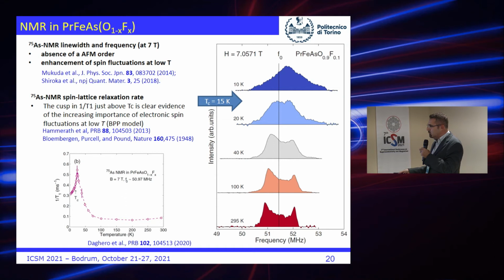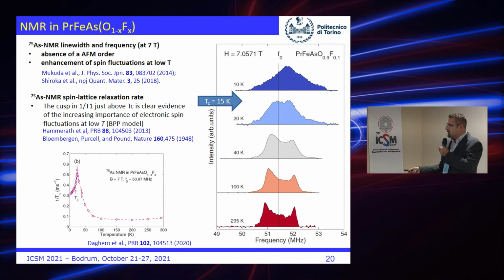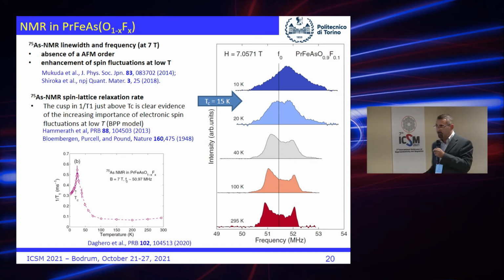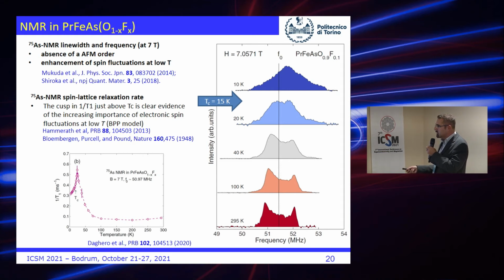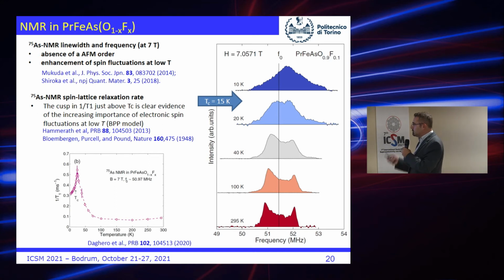There is a peak that actually occurs slightly above Tc. The reason why this is suppressed, in principle it should continue to grow, but it is suppressed for some reasons that have to do with superconductivity, according to this model here that has also been used in another 1111 compound in this paper. Anyway, spin fluctuations are there.